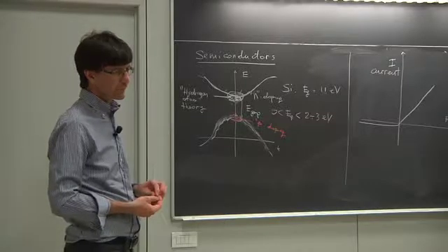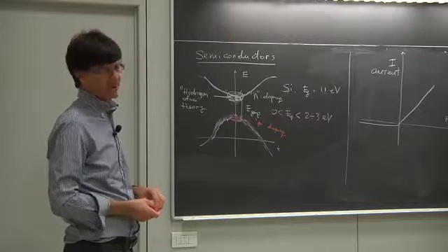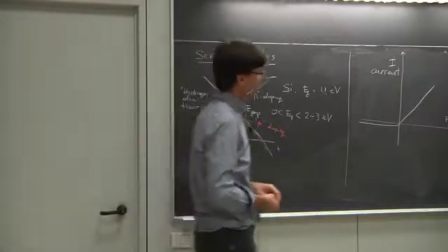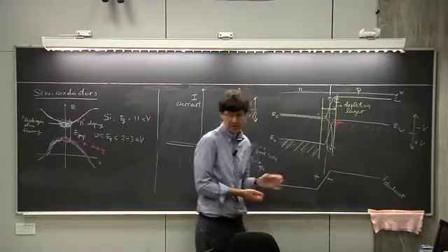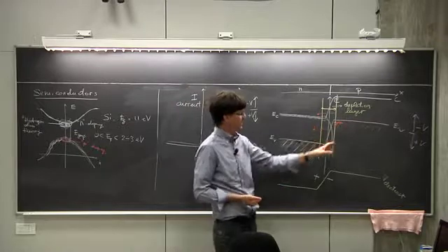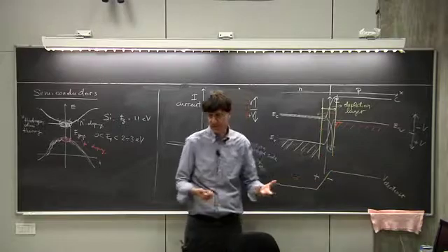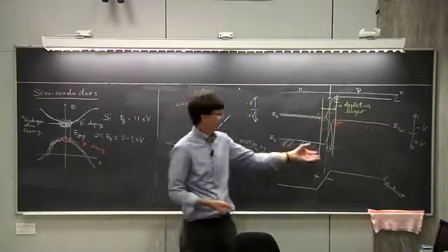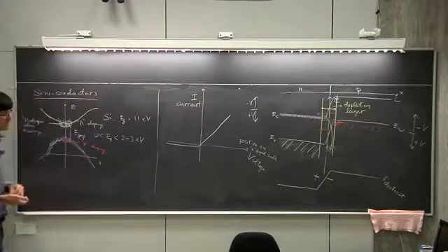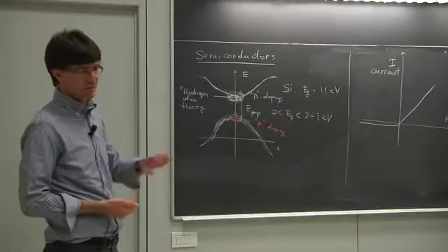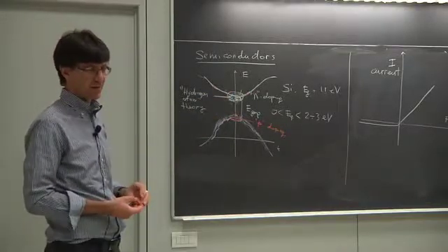What's the scale of devices for which we have the same physics, at least? I would say of the order of microns, a few microns. For example, your system needs to have a depletion layer which is small compared to the size of your system. Otherwise, this will be the entire system. If this is, say, 100 angstroms, your device cannot be smaller than that, because otherwise everything becomes a depletion layer, so it's meaningless. So I would say that down to the size of, say, 10 microns, this kind of physics is still dominating. Below that, it's a different story, clearly.